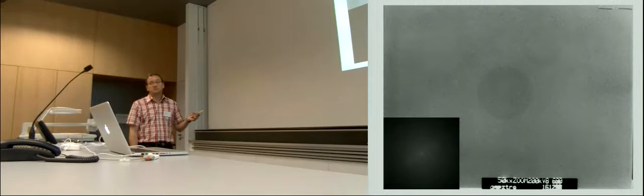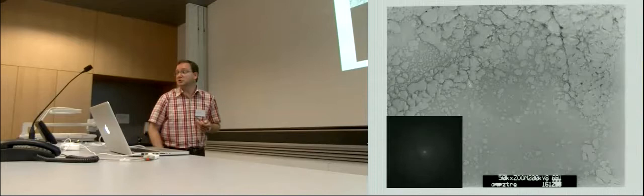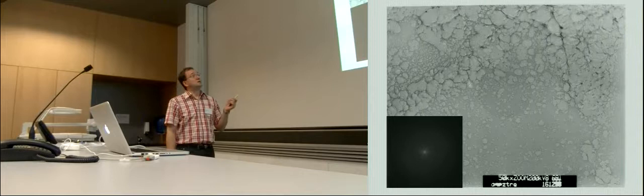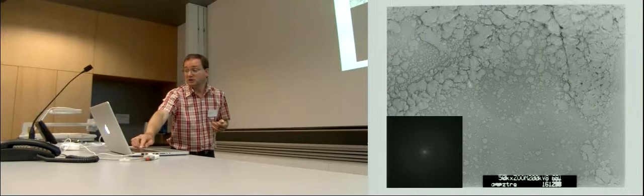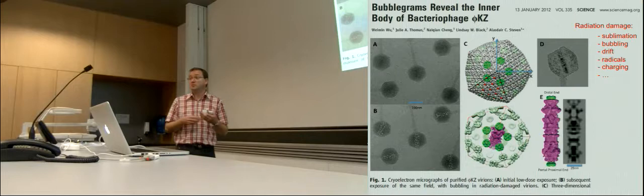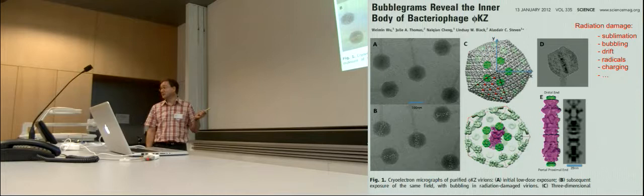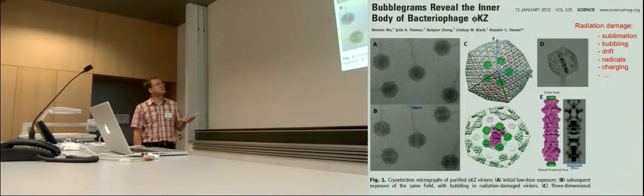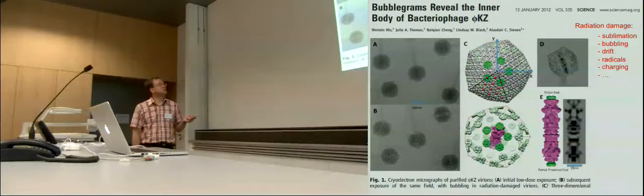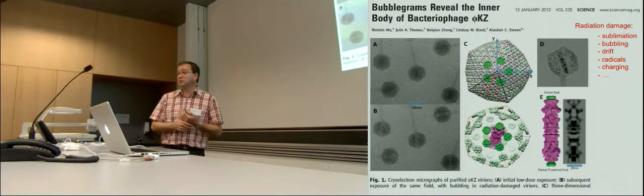You actually would only see spots if you do a diffraction, Fourier transform. This is the first exposure. When you go to the second exposure, you have a lot of contrast, but you lose a lot because you do really damage the sample. Electrons interact so much that they damage everything. So you see that one effect is, for instance, bubbling. And bubbling is not useful. Apart from these people that can publish in Science in 2012, the bubbling of the inside of a bacteriophage. So here the bubbling is used to show where the metal sits, where this structure in the head of the bacteriophage is sitting. But actually radiation damage is a main problem in electron crystallography.